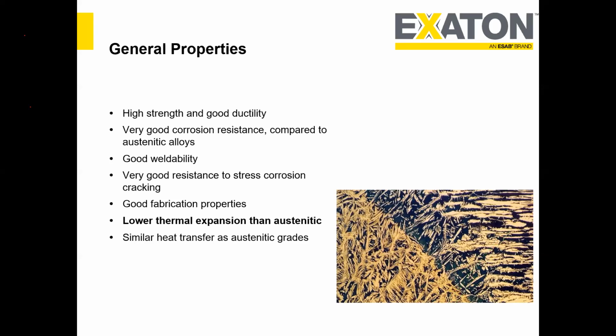There's an interesting background basically. Austenitic stainless steel 316L or 304L is basically 18-8 stainless steel, so typically around 18% chromium and 8% nickel. And nickel is one of the most expensive alloy elements. If you see the chemical composition of lean duplex 2304, it has 23% chromium and 4% nickel. So eventually we managed to make it with half of the nickel content compared to stainless steel 316L, and the cost was drastically reduced. At a later stage, when 316L became a commodity and its price dropped, the costs became comparable. So in terms of applications, we expected lean duplex to replace 316L, but it really didn't happen in the industry so far.